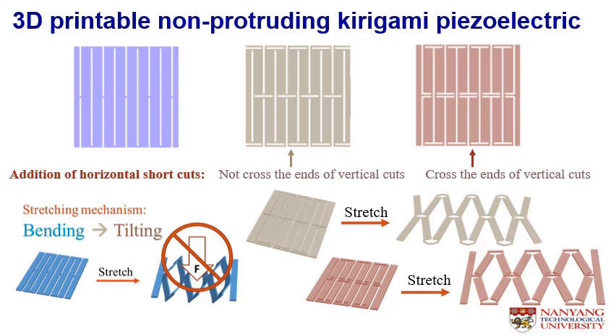Typically, in a kirigami structure, upon stretching, there will be tilting out of plane. In order to avoid this issue, we have added horizontal short cuts at 2 locations. One is without crossing the end of the vertical cuts, and the other is crossing the ends of the vertical cut.